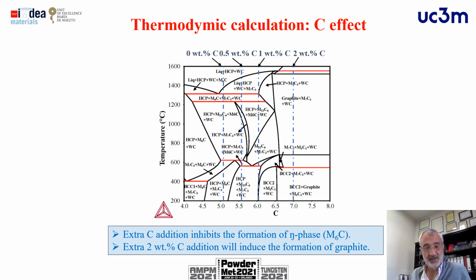Previously, we have tried to see what happens in terms of the possible carbide formation with addition of carbon to the tungsten carbide. Later, we will test different amounts of carbon between 0.5% and 2%, but the highest levels of addition of carbon can produce the formation of graphite, which is not a good idea in terms of the final properties. So later we will see that the best combinations are near to 0.5% of carbon additions.